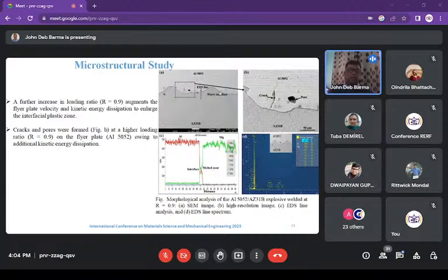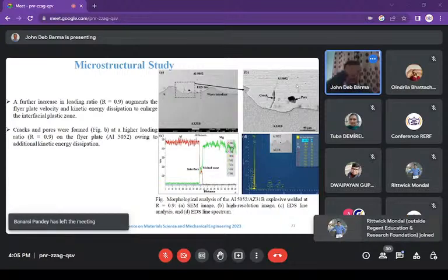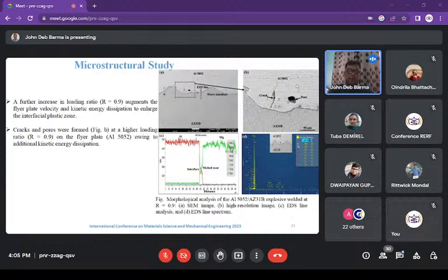Okay. Now, in contrast to the lower loading ratio, that is when R was kept at 0.7 as well as 0.8, cracks and pores, as you can see here, cracks as well as pores, these are observed for the highest loading ratio, that is at 0.9, and which is near to the interface. And that is happening due to the dissipation of more energy and additional kinetic energy dissipation. That is the reason. And the additional energy that is available after creating the undulating surface, as you can observe, led to crack and pore formation.